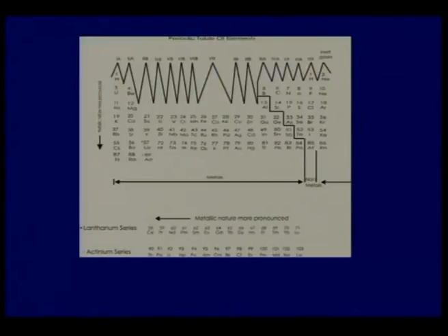Something like lead can be very easily converted to oxide, and very easily reduced by carbon, because carbon will take out the oxygen and lead will be left behind. So, these are the techniques of breaking the compound to liberate the metal, and all extraction processes in a sense are processes of liberating the metal from its state of association with non-metals like oxygen, sulfur and halogen.